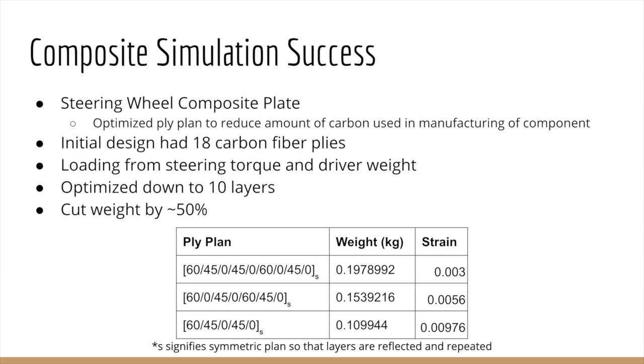You can see that the strain of the 10-layer component, which is the bottom row, is symmetric, so you multiply what I show by 2. The strain is 0.009, which is much under the 0.017 that I said was a failure rate, with about a safety factor of 2, which is what I was designing for. I also was able to cut weight from the initial 18 layers to the 10 layers, a weight savings of about 50%, which is pretty significant in our vehicle.